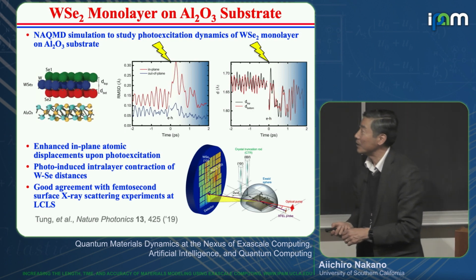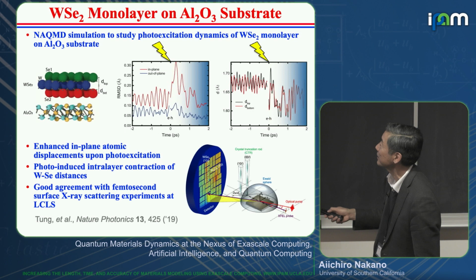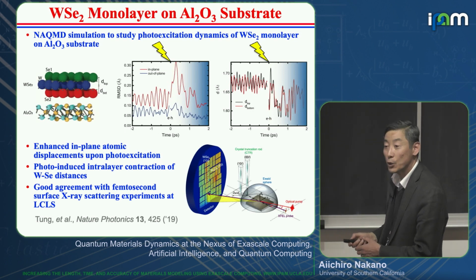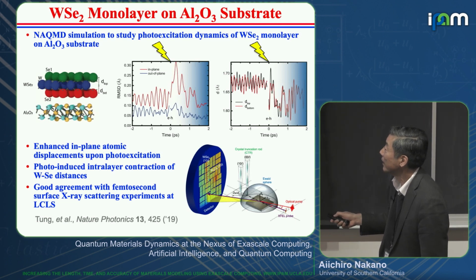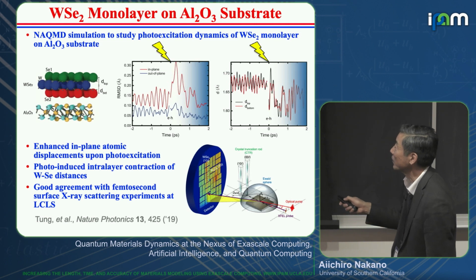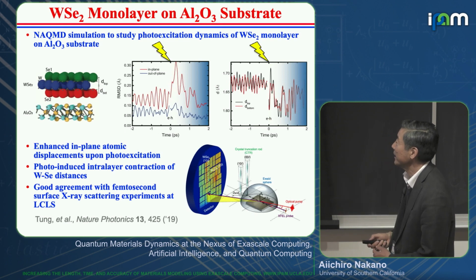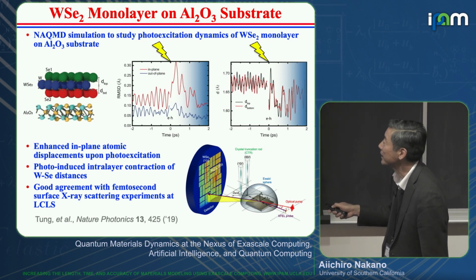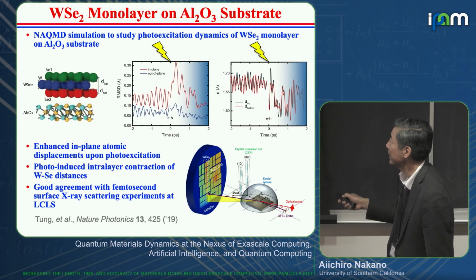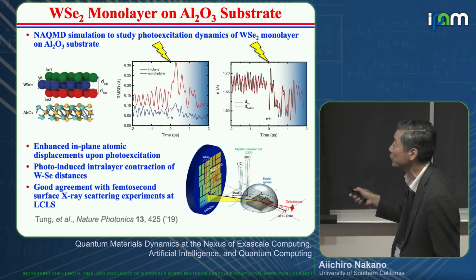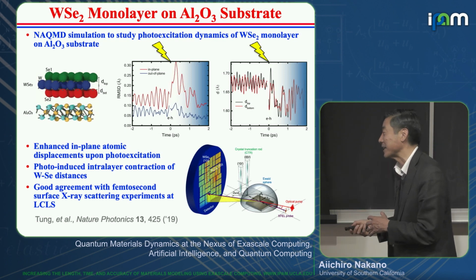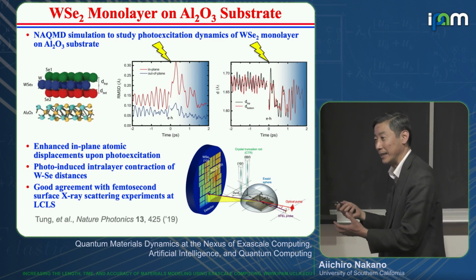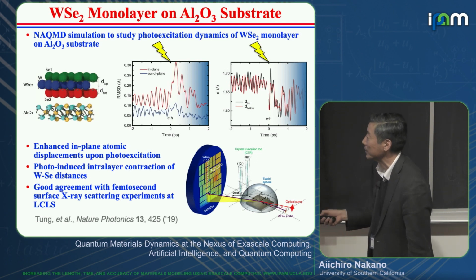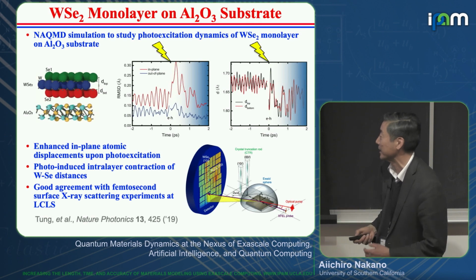And then after that, we also simulated photoexcitation dynamics in a tungsten diselenide monolayer on an alumina substrate. And this shows the root mean square displacement of both in-plane and out-of-plane atomic motions as a function of time. So upon the photoexcitation at time 0, we see enhanced in-plane atomic motion. And this shows the distance between the top and bottom tungsten selenium layers. And we see, upon the photoexcitation, a photo-induced contraction of the tungsten selenide distances. And this can again be explained by the change from bonding to anti-bonding character through the photoexcitation. And this is in good agreement with the femtosecond surface X-ray scattering experiment at LCLS.